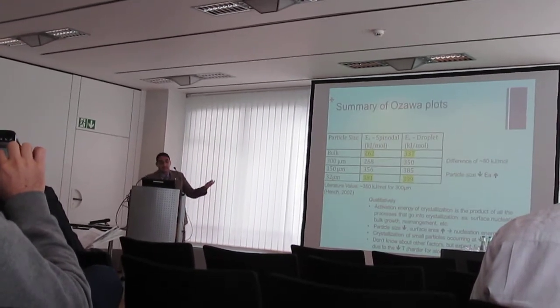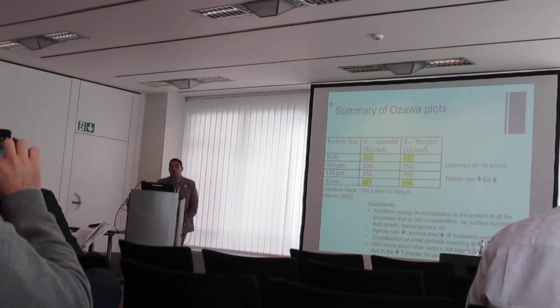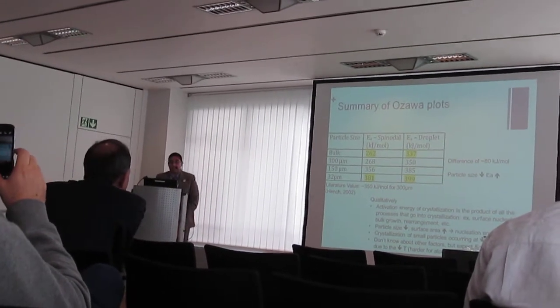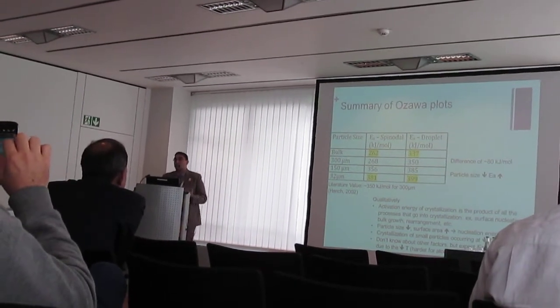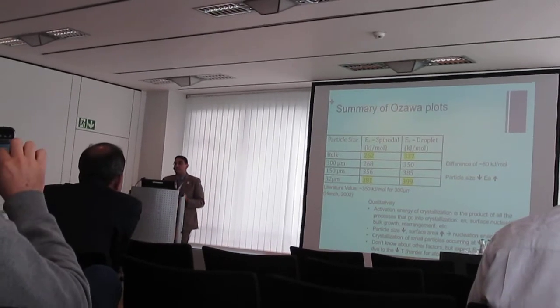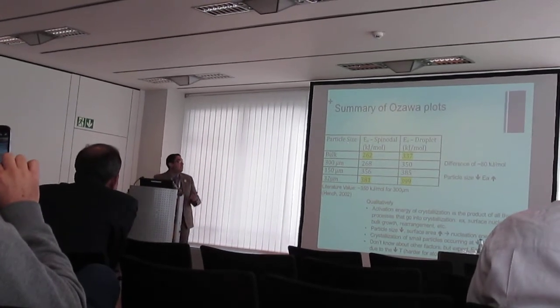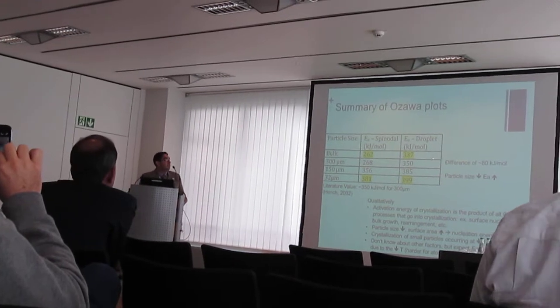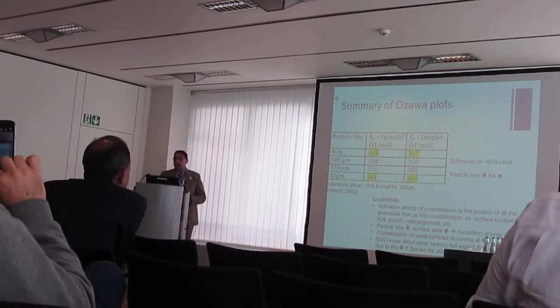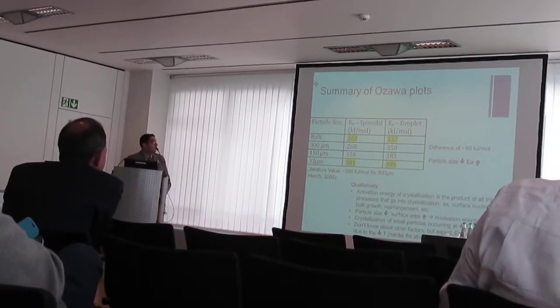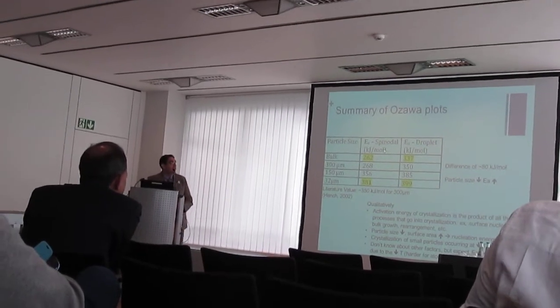This is a summary of the Ozawa plots that I talked about. Now there are 2 different things I would like to point out in this summary slide. The first thing is that there's a big discrepancy between the activation energy of crystallization for the bulk glass for both the spinodal and the droplet glass.